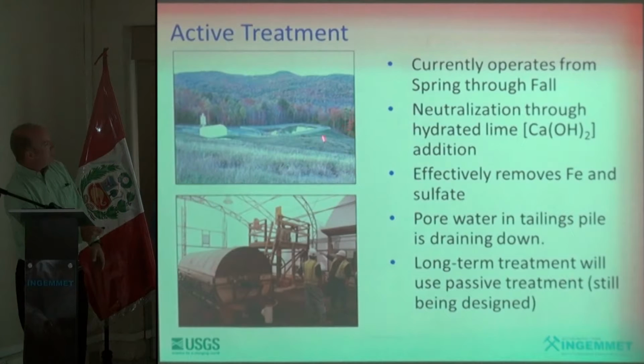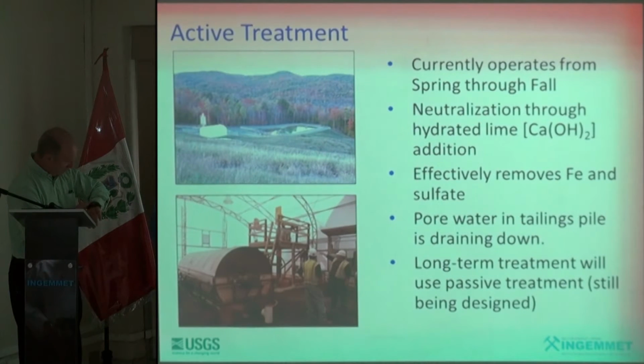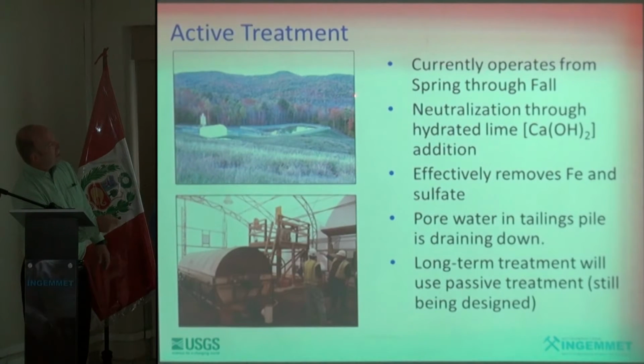So they built this active treatment plant at the base of the tailings pile, which is shown here. It's only run from the spring to the fall. Everything is frozen in the wintertime. And basically what they're doing, they're neutralizing the mine drainage by adding hydrated lime, calcium hydroxide, which is added here. It then goes into this rotating drum where the waters are mixed, and then it's just discharged out to the settling pond. And this has done a very effective job at removing iron and sulfate.